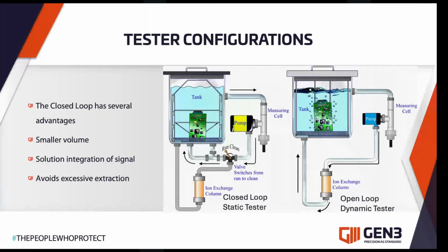There are some differences in the available equipment around, and you have a closed loop or a static tester, and you have an open loop or a dynamic tester. The big difference between these machines is the amount of volume in the ancillary pipe work. In the closed loop system, it shuts out the ion exchange column, which is used to clean the liquid before the test. In the dynamic or open loop tester, the ion exchange column is always in the loop. So the volume in the system is greater. And this volume is important because you divide the contamination by the volume in the system to get your loads. If you've got a bigger volume, you've got smaller sensitivity.